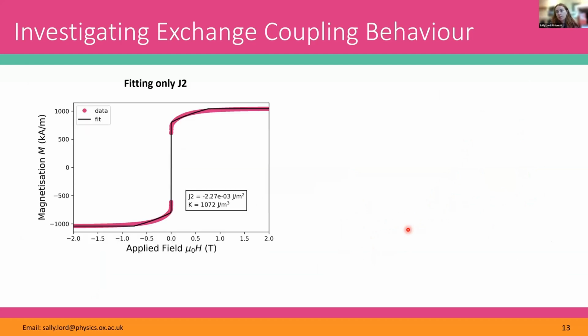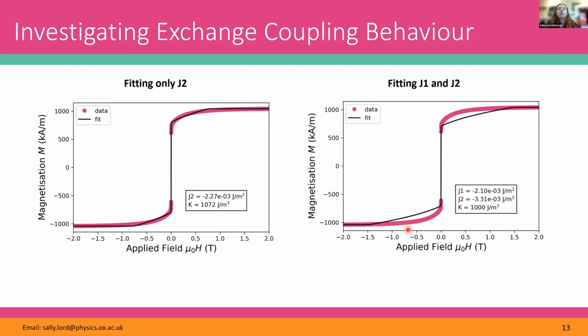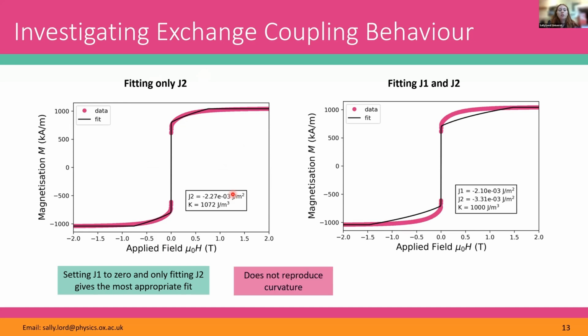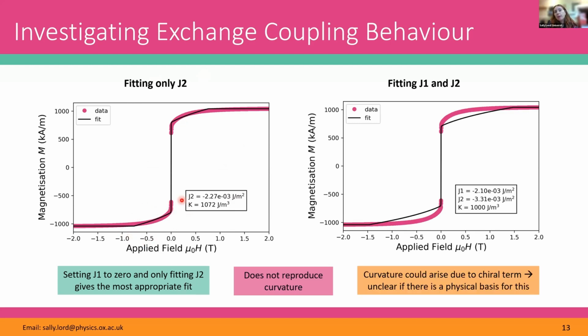So we went back to the simulations and we fitted the magnetization loops to the data again, but this time we set J1 to 0 and we only fitted J2. And you can see that the fit is much better when you set J1 to 0 and only fit J2. But still, we were unable to reproduce this nice curvature that you see in the experimental data. And it's unclear where this curvature arises from. It could be due to some sort of chiral term, but we are still investigating this. It's unclear if there's a physical basis to this.